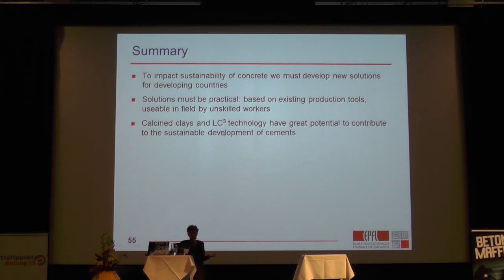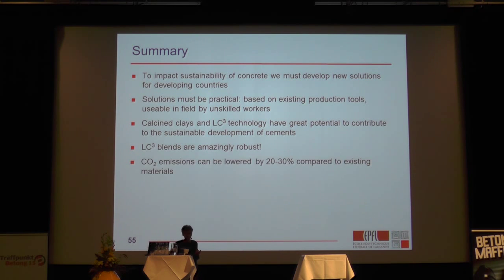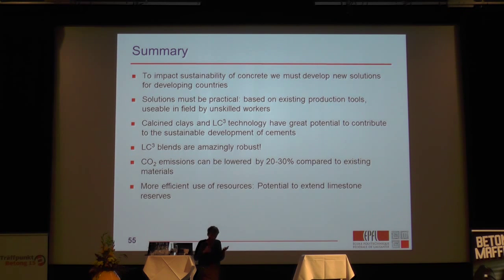In that regard, I think calcined clays and this LC3 technology have a huge potential. Probably not the only thing, but it has a big potential, and they're amazingly robust materials, which can reduce CO2 emissions by 20 to 30%. And also, I didn't really talk about this, I didn't have time, in many countries like India, in fact, we're running out of things like limestone.